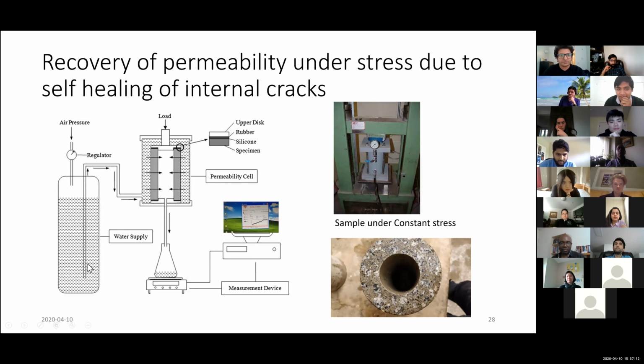There is water inside the system, right? This water is what I used for the first 24 hours of observations. And then I removed all this water, from here as well as from here, and put inside the cylinder a saturated sodium carbonate water and used that again for doing the same test with the same sample. So after it had seen a reduced permeability, I used that same sample again and tested it for the next 24 hours under a saturated sodium carbonate water.